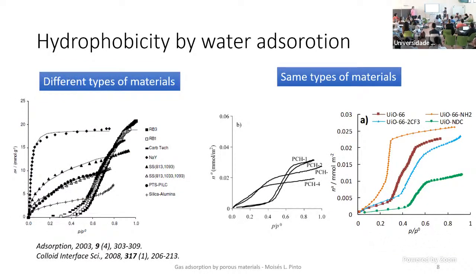Another way of using adsorption is also to characterize the chemistry of the surface. We can use, for instance, water, in this case, these are water isotherms, to see if we have more polar or more hydrophobic materials or more hydrophilic materials or surfaces. Yes? So you see here, for instance, in this case, this very steep isotherm here corresponds to, where is it? Here, NaY zeolite. So you have cations inside at the surface, and of course, water likes to hydrate these cations. And when we put even very minor amount of water, the adsorbed amounts are increasing like this. Yes? Then, of course, you saturate the material, it doesn't increase anymore.